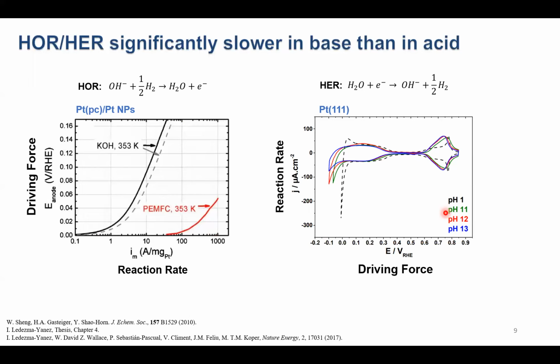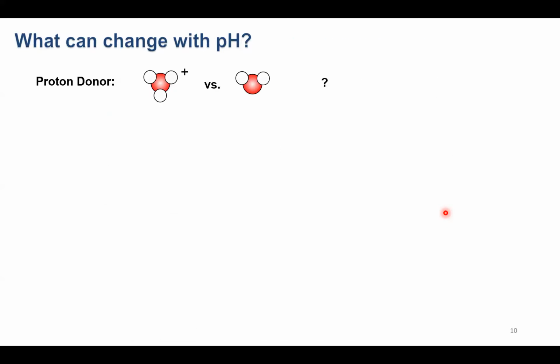And so we might ask, what can change when we change electrolyte pH? Right? First, we could change the proton donor. If we have a simple electrolyte, we might switch from having H3O+ as our proton donor in acid, to water as our proton donor in an alkaline electrolyte. And maybe the kinetics of pulling a proton off of either of these molecules is different. And so recent work out of the SUNCAT and CAT theory groups showed that this is exactly true for hydrogen evolution on platinum, where the barrier to pull a proton off of H3O+ to stick it on a platinum surface is much, much lower, almost barrierless, than it is to pull a proton off of water, which is what we would have at high pH.